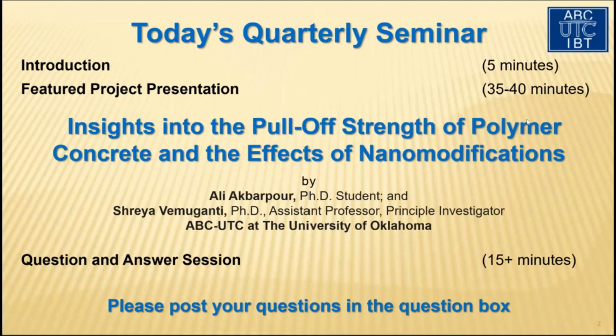So yes, the time of placement does affect the pull-off strength, because if you consider it, what kind of failure is seen is governed by the different strengths, right? You have the overlay, you have the interface, and you have the substrate. So if the substrate is weak, you will see lower strengths, and you might see a failure more in the substrate than in the overlay or the interface. Now, in practice, the type of failure mode that you'd like to see is in the substrate. You want the bond for the overlay and the concrete to be strong enough, and that value is that 250 psi